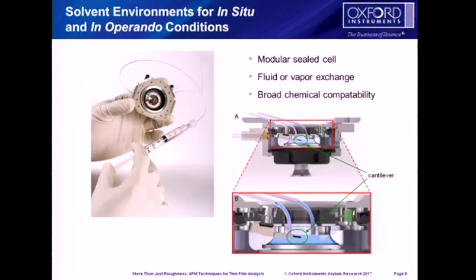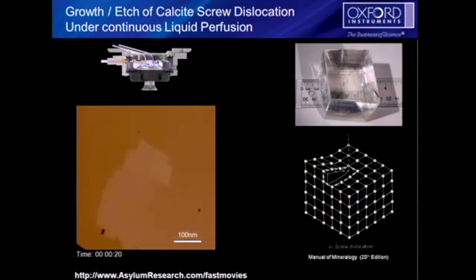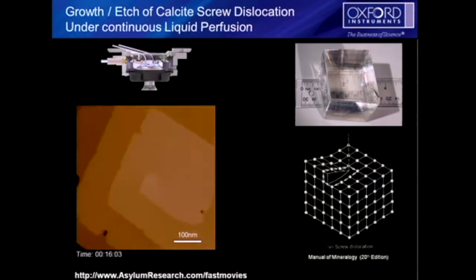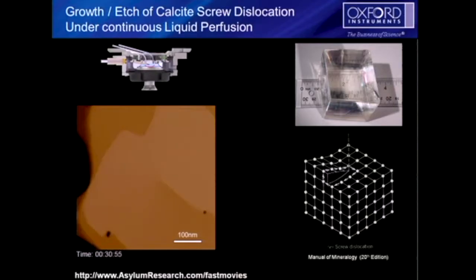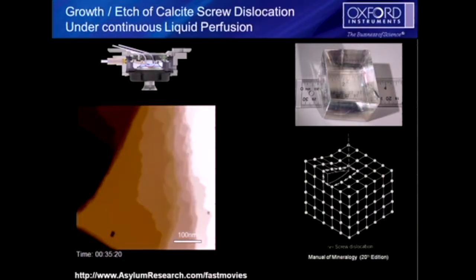Now going one step further, what about controlling the environment around your sample? So whether the films are grown using an electrochemical process or they are grown in a controlled environment, the instruments are capable of creating a hermetically sealed cell and passing gases or liquids that you desire. And you can do some really interesting experiments where you can see controlled deposition rates, single atomic layer at a time by doing a controlled experiment in a sealed cell. So in this example, every subsequent AFM image was laid on top of each other, and we can visualize a simple screw dislocation frame by frame and then lay all these images over into a video. And you can then reverse the voltage and cause an etch to happen when you remove all of these films. So it's a pretty interesting example on how you can use temperature and environment control to study these processes very accurately and with a lot of detail.